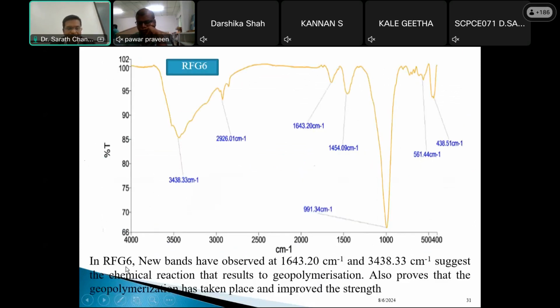And in RFG6, new bands were observed at 1643.20 and another band at 3438.33 per centimeter, which suggests the chemical reaction that results in geopolymerization. So these bands, at these two values, indicate that geopolymerization has happened.